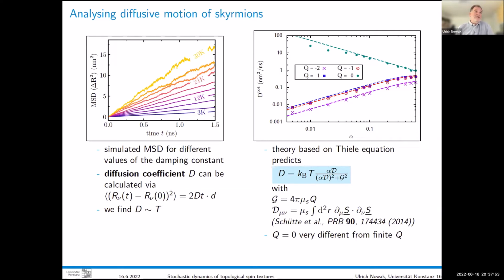But anyway, there is a theoretical forecast that the diffusion coefficient should behave like this, k_B T, and then this fraction here. And that depends on two quantities, or three. One is the Gilbert damping constant, but the other two quantities are D and the G. The G is the topological charge, more or less, with some prefactors. So that is a quantized quantity, something like 1, 2, 3, or so, depending on the topological charge. And that's what we play around with here in this graph. And the other one is another integral. That's not the topological charge, but it is the integral that characterizes how the spin structure is twisted.